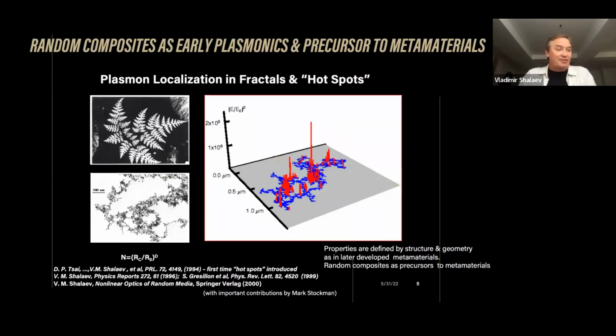Interestingly enough, the field of plasmonics was first developed for rather complex systems, random systems, which often have fractal morphology for the reason that they grow this way. And fractals are actually structures that reproduce the morphology, the geometry of the whole structure, on a progressively smaller scale, either deterministically, like in the case of this fern, where you could see that the structure of the whole is repeated on this scale and on this scale and so on and so forth, or statistically on average, like in the case of this fractal aggregate of silver colloidal nanoparticles.